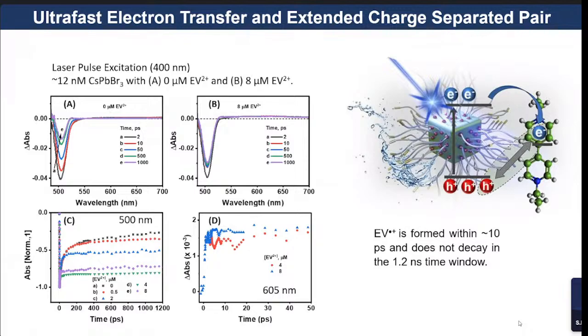Allow me to ask more. Yeah, of course. Suppose I have that, when you are taking the singlet and triplet, when it changes the structure. No, because when you exchange the halide, it's the same thing. We stir with iodine, which is very sparingly soluble. So it just kicks out the bromide and gets iodide. All the ligands, everything is in there. Nothing changes.